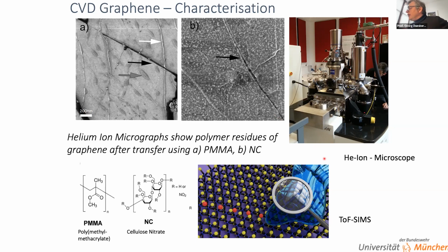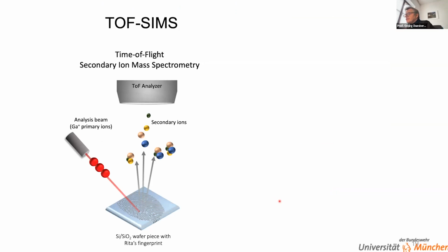So we started to look into this type of contamination with a new method, because actually this machine is notoriously difficult to operate. We used TOF-SIMS, an instrument which we have. So TOF-SIMS is maybe familiar to those who worked in the semiconductor industry. It's usually used for looking at doping profiles in semiconductors. So what it essentially does, it shoots primary ions onto the substrate and then sputters away the elements from the surface, which then go into an MS mass spectrometry analyzer.